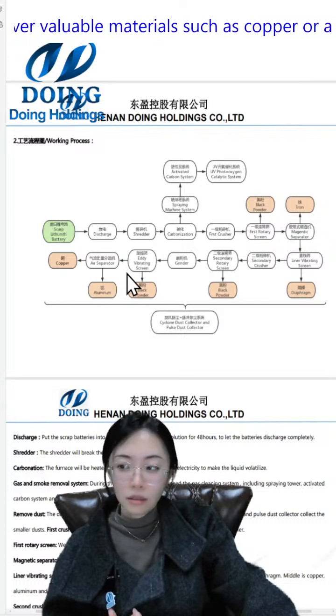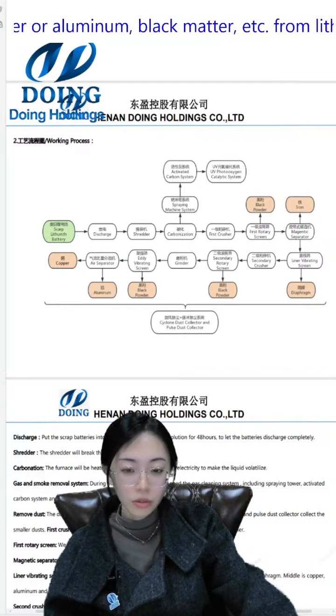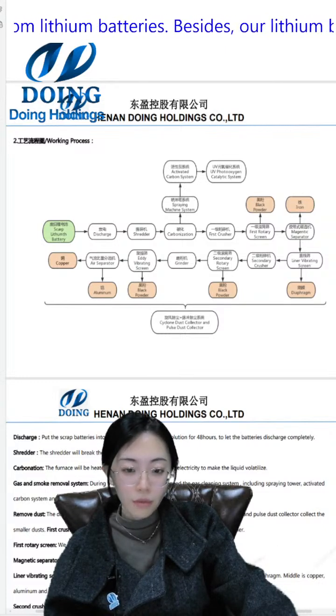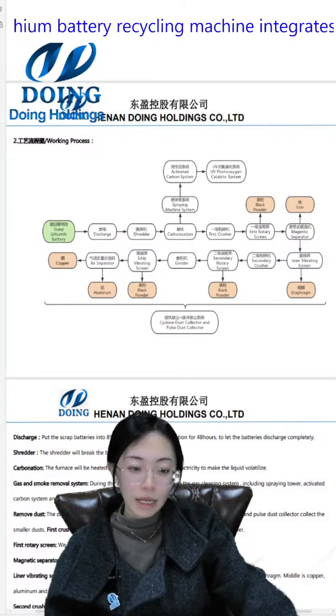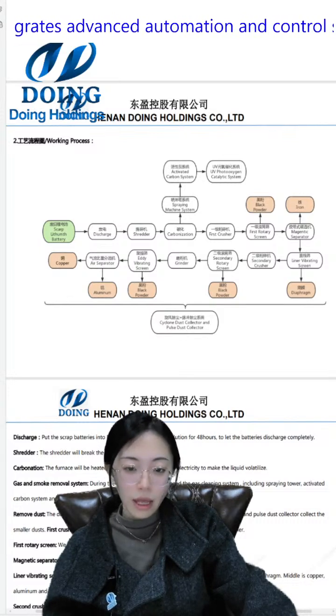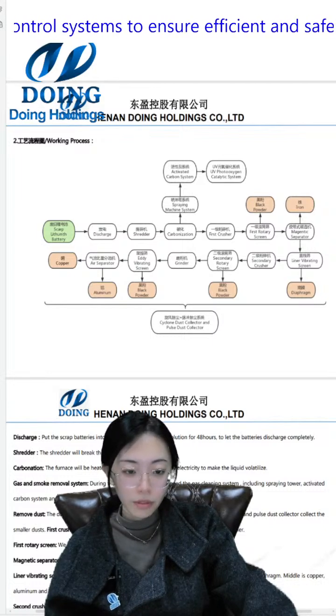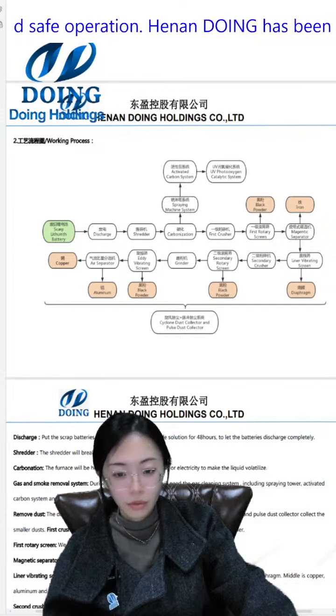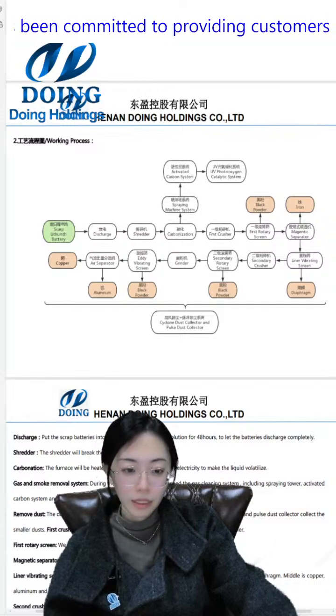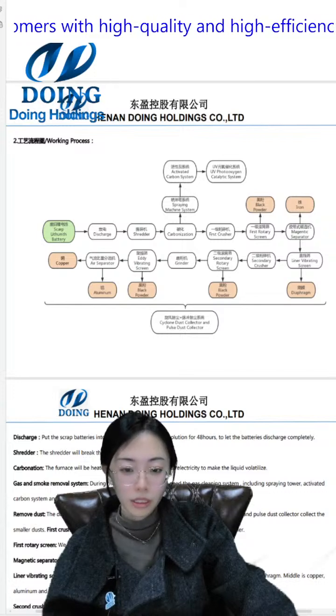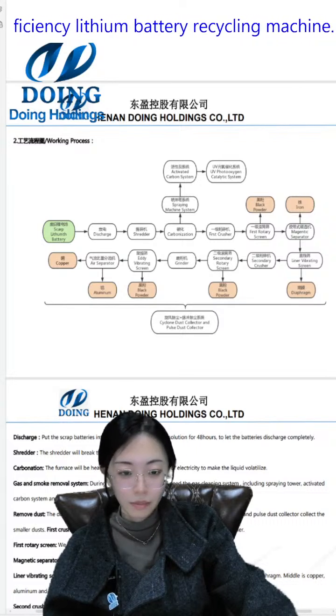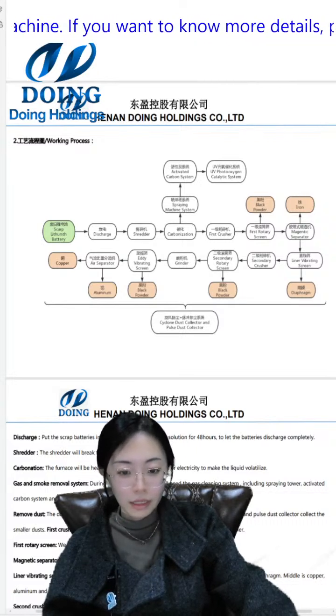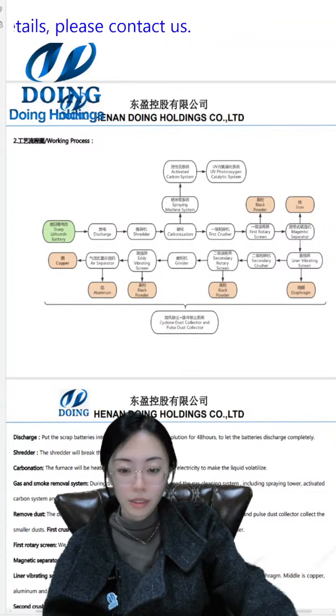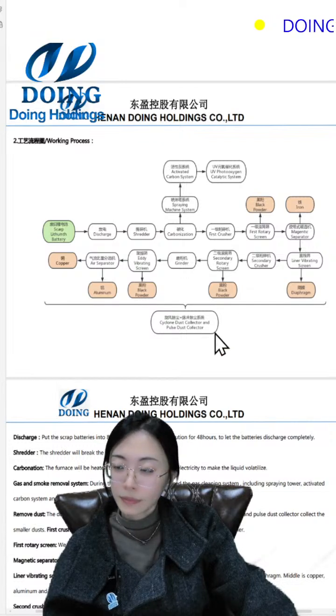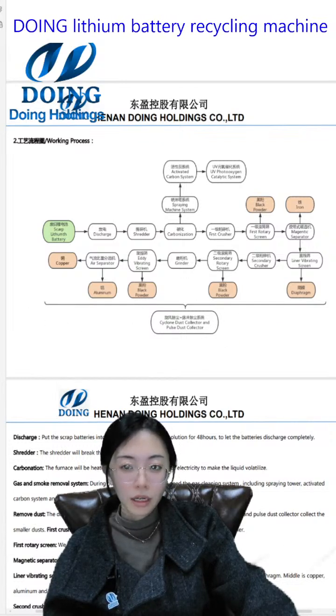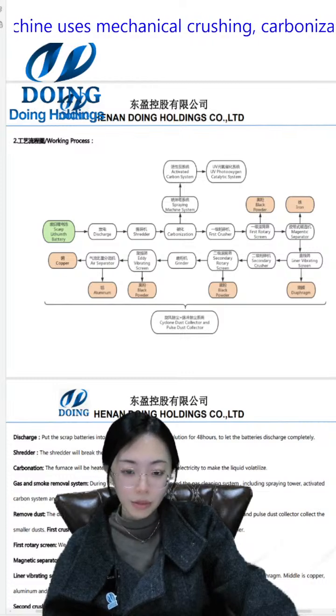And when it comes to the copper and aluminium, they will go into the air separator, or called the air gravity sorter, which utilizes the combined action of airflow and vibration on the materials. So the larger copper particles will settle to the bottom, and the smaller aluminium particles will suspend on the surface of the raw material layers by the action of the airflow. In this link, the recovery rate of the copper and aluminium is about 98%. So this is the whole production line of the raw materials of the lithium battery recycling equipment.